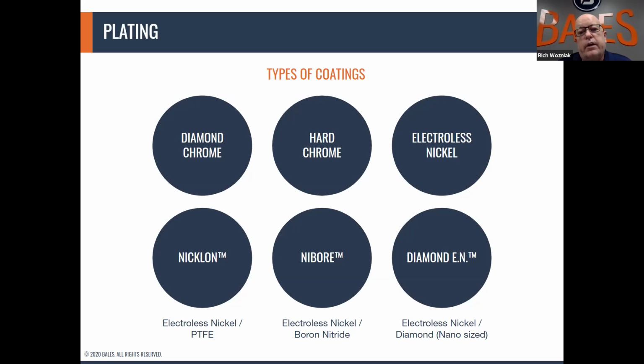Electroless nickel, you're looking at corrosion protection as the key, especially if you're in a harsh environment. High phos is recommended. So when you're looking to spec out an electroless nickel, if you're looking for corrosion protection, always ask for high phos. Mid phos will give you good protection, but high phos will definitely be a greater asset to you in certain situations.